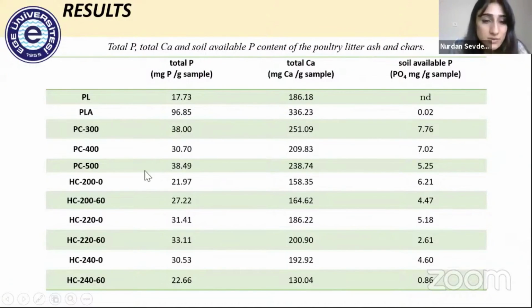When we compare the total phosphor amount of biochars, it is clearly seen that during pyrolysis, phosphor remains mostly in the biochars. Available phosphor decreased above 400 degrees, probably due to the formation of insoluble phosphate salts like calcium phosphate. In hydrochar carbonization, also hydrochars contain